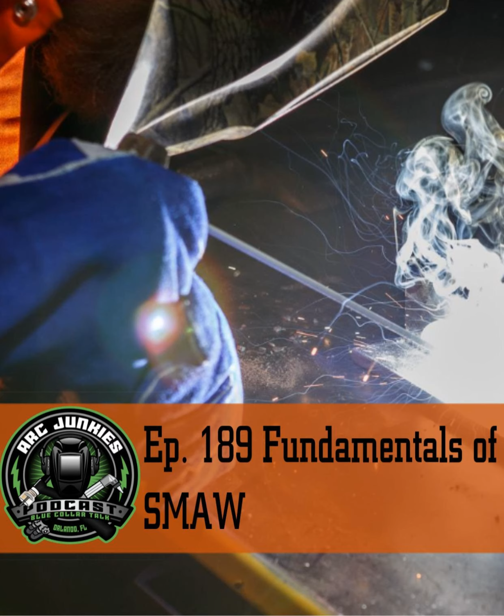But one thing you have to consider is if I'm running a machine at my house and I only have about 10 foot of lead between my workpiece clamp and my electrode lead, 125 amps is exactly what I'm getting. But for every 50 foot of cable that I run out, whether it's on the negative or the positive side, for engine drive applications, I need to add 5 amps because there's going to be roughly a 5 amp drop.